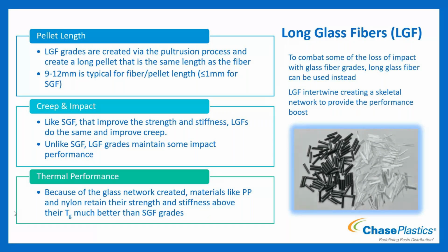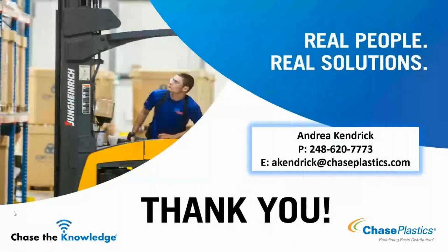And now when it comes to that, it will also affect your shrinkage. So fillers with higher aspect ratios will have a tendency toward more anisotropic shrink, whereas fillers with a lower aspect ratio will typically exhibit more isotropic shrink.